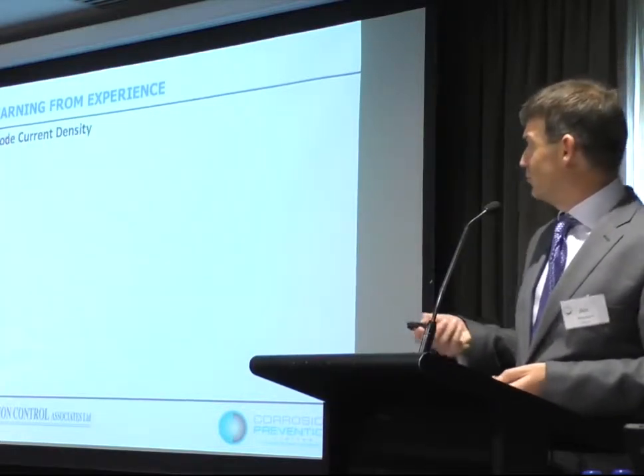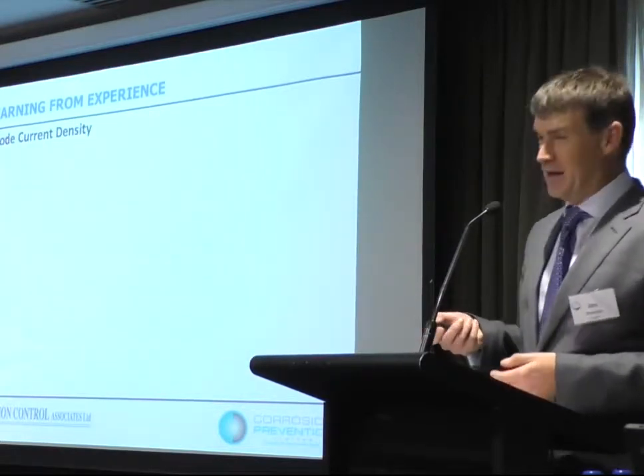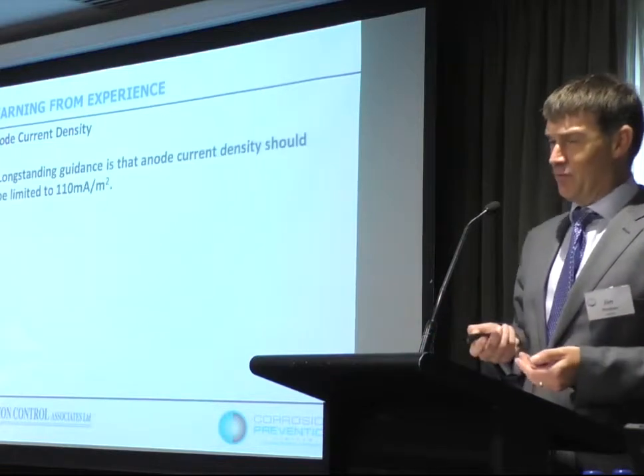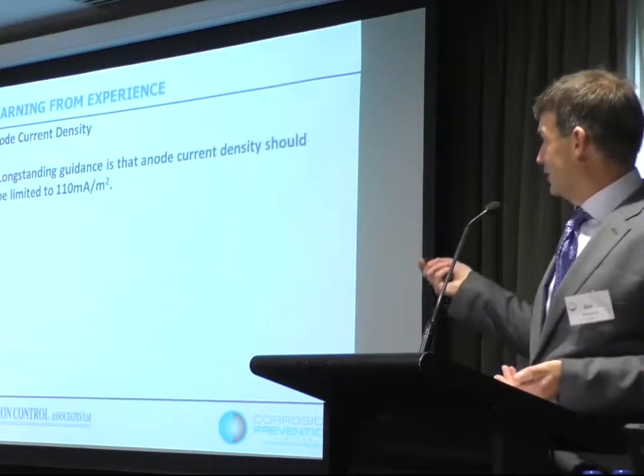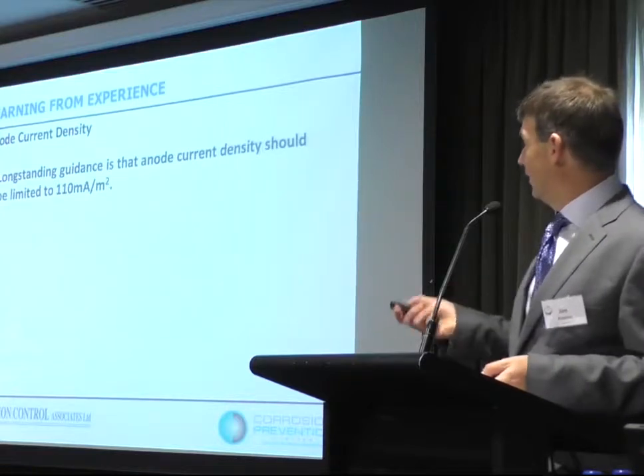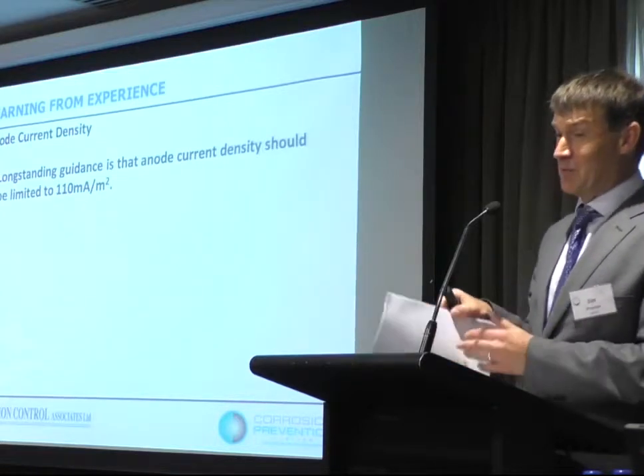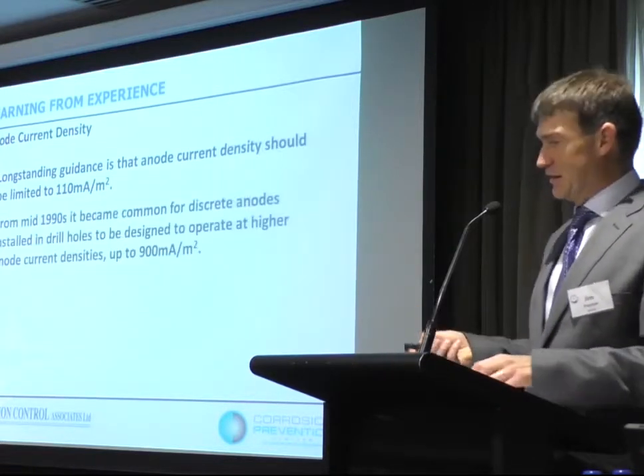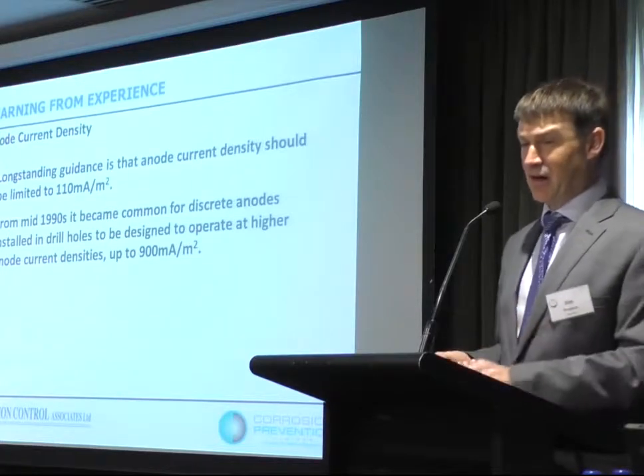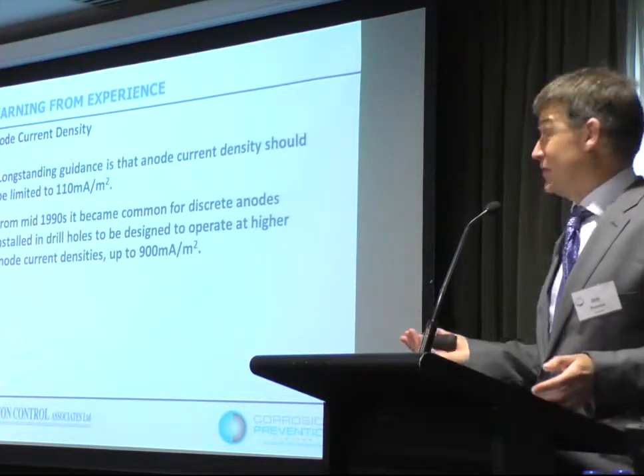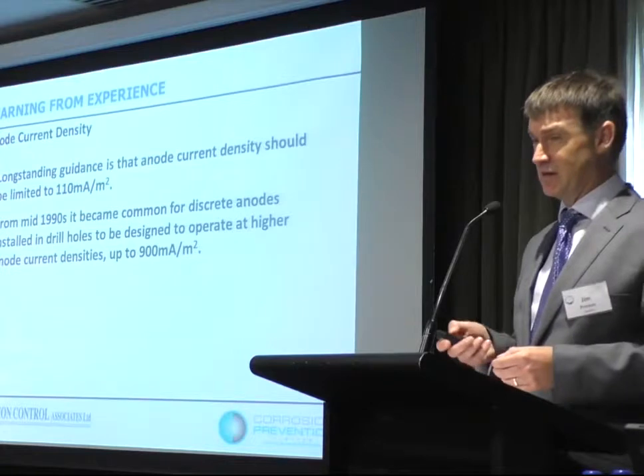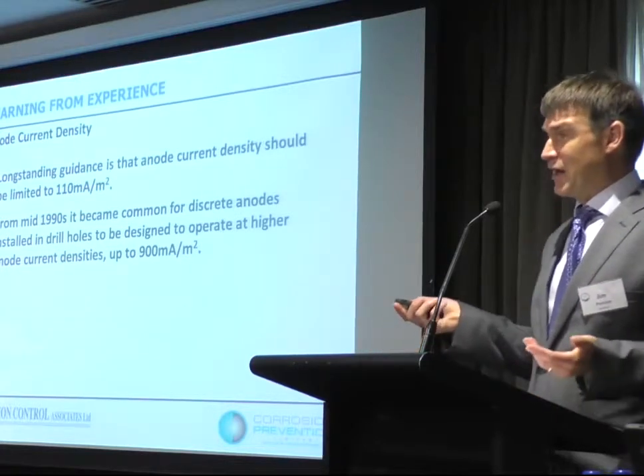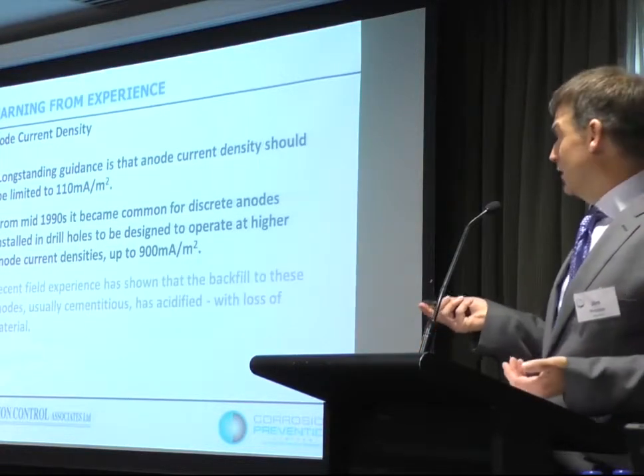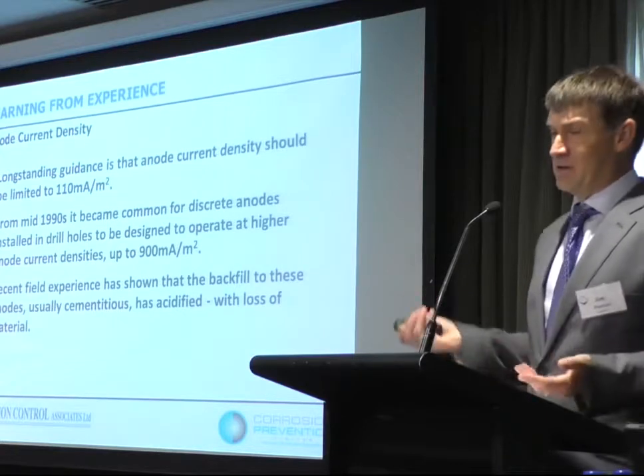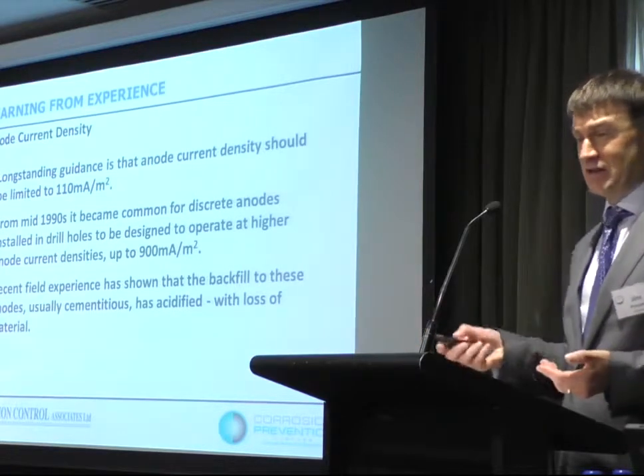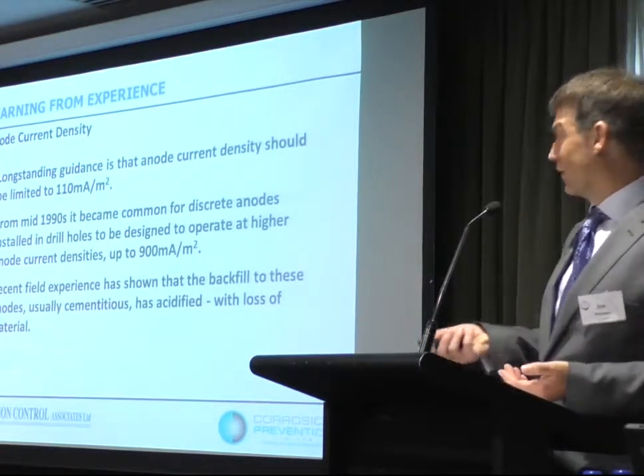I'm just going to quickly run through the next ones. Another issue we found from our experience anode current density, long-standing guidance is that we should limit that to 110 milliamps per square meter. In the 1990s, we started designing discrete anode systems in particular at much higher anode current densities. And we're now finding that in quite a few instances where that's been done, the backfill to these anodes, which is normally cementitious, is starting to acidify or deteriorate.